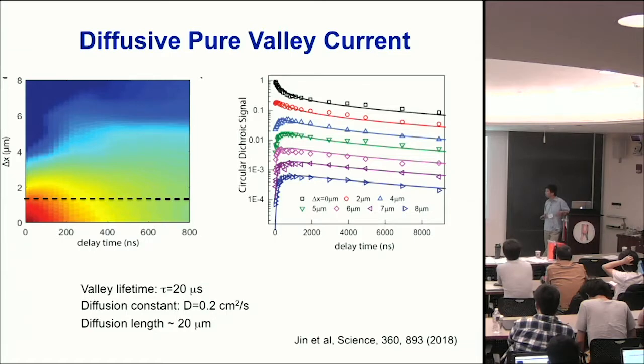So that part, I think, is partly defect related. If you have low doping, you are close to the mobility gap, then the mobility will be lower. The best mobility in TMDs people usually observe is in highly doped samples. On the other hand, I do feel like this long-lived spin is not because of purely localized states. They might stay in a defect a little bit, but overall they certainly can propagate. They are still moving, they have well-defined transport properties.